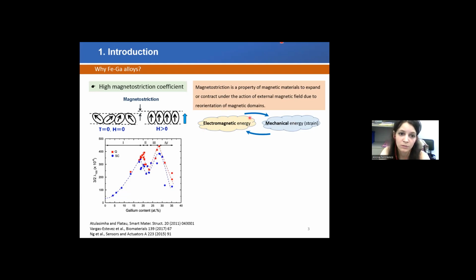We also know that the magnetostriction properties strongly depend on the composition. So, for example, here we have the change in magnetostriction coefficient as a function of gallium content. There are two maxima that correspond to 20% of gallium or 30% of gallium. So these are the two compositions that we will be trying to achieve in this work.